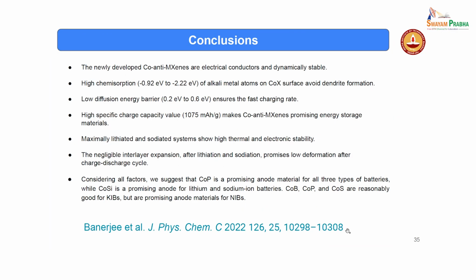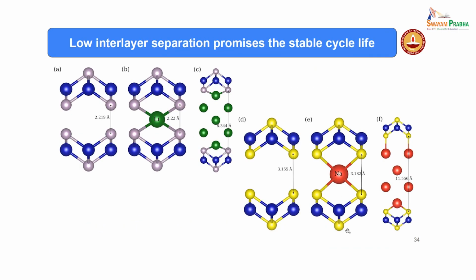We have also finally considered how much, with the adsorption of these materials, there will be an increase in the interlayer distance. This is to know whether your batteries will be bulging out or not at the end. We saw that the amount of change for a single layer of lithium atoms is pretty little. Even for the case of sodium, it is very little, suggesting that the low interlayer separation is useful for the stable cycle life of this battery.